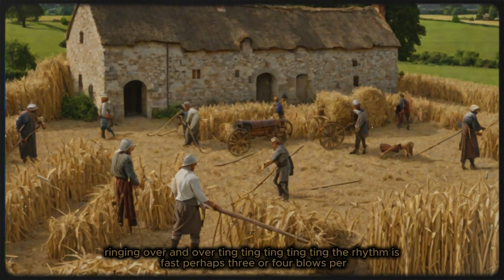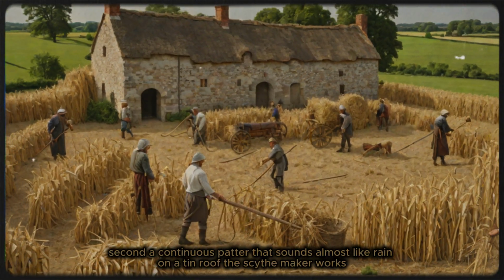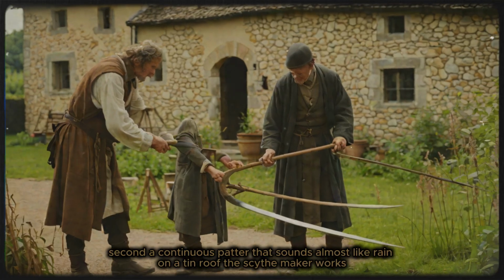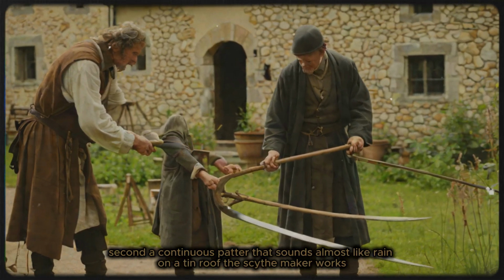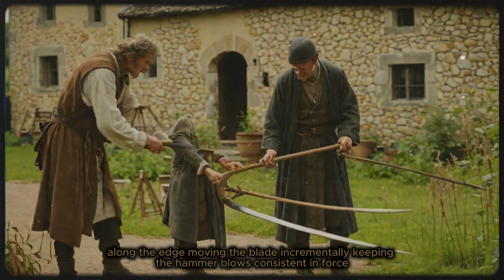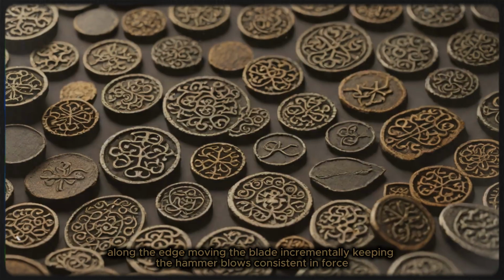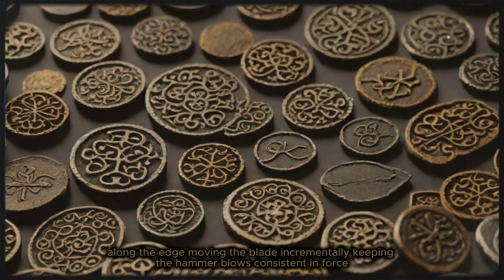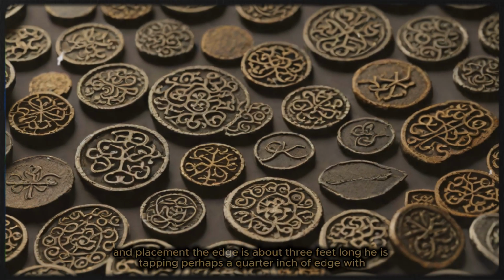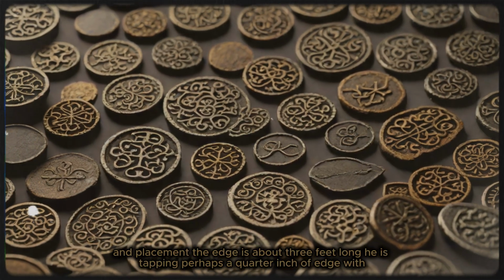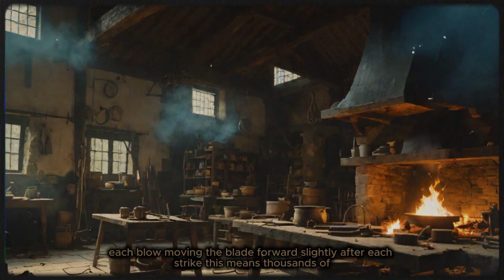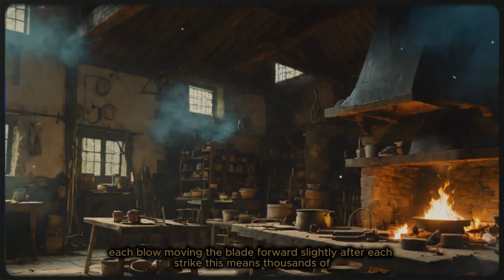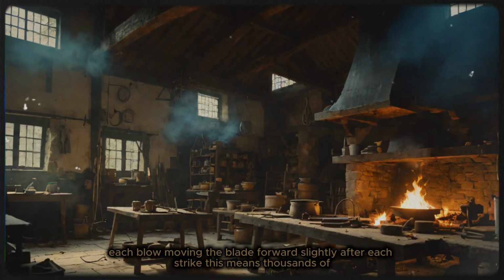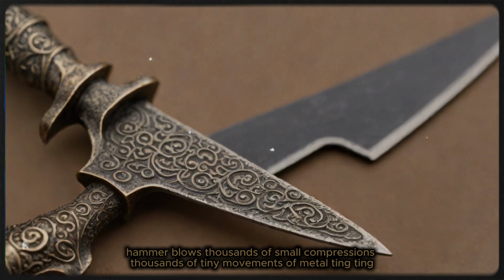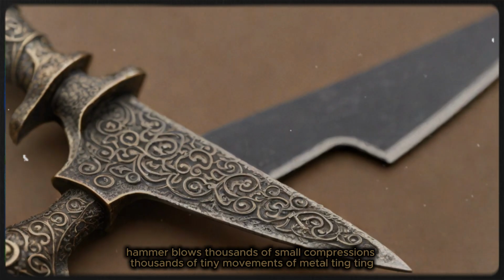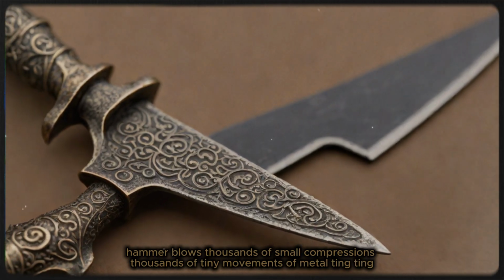The rhythm is fast, perhaps 3 or 4 blows per second, a continuous patter that sounds almost like rain on a tin roof. The scythe maker works along the edge, moving the blade incrementally, keeping the hammer blows consistent in force and placement. The edge is about 3 feet long. He is tapping perhaps a 1/4 inch of edge with each blow, moving the blade forward slightly after each strike. This means thousands of hammer blows, thousands of small compressions, thousands of tiny movements of metal.